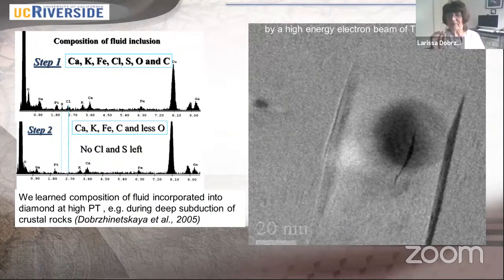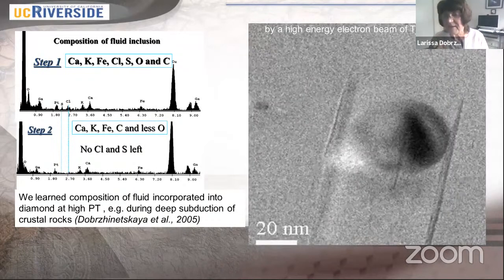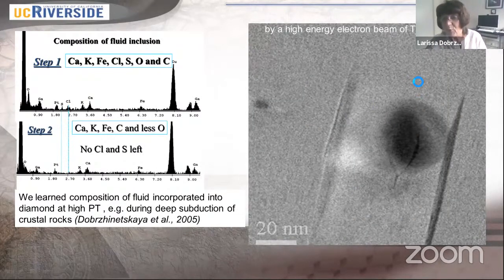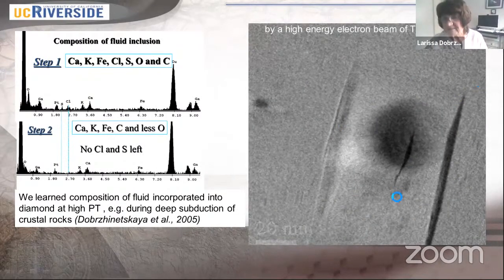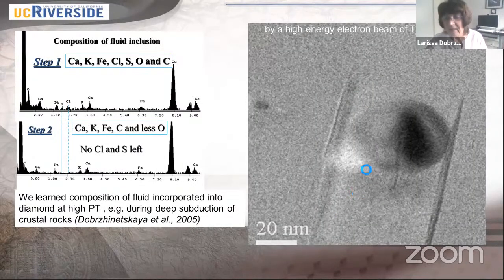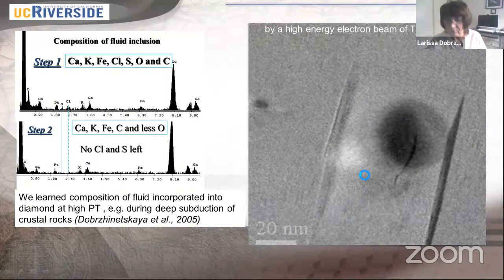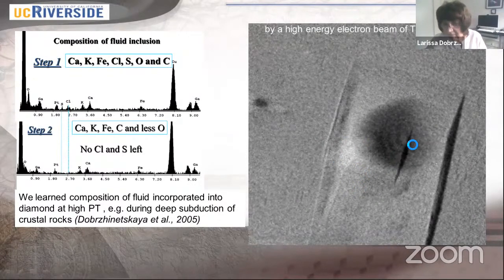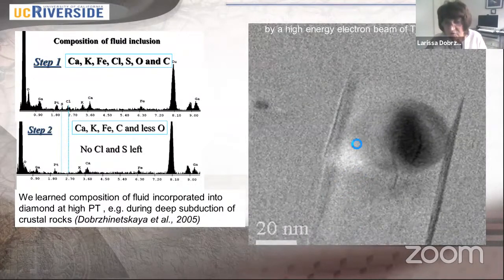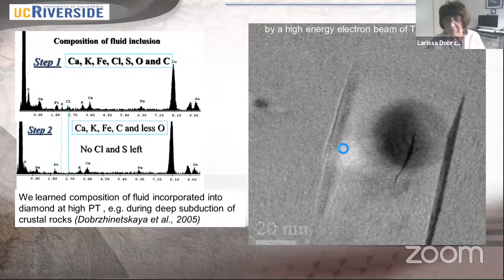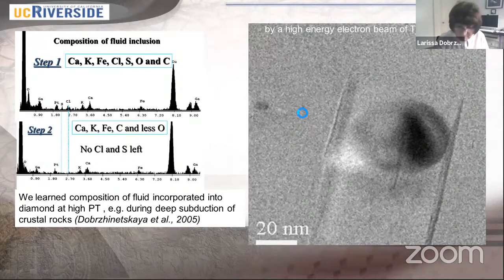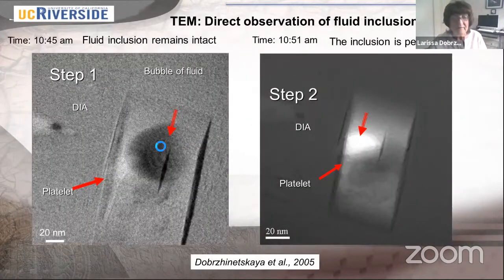Here, you have to start to think very fast. What does it mean? Because you see, it's probably a bubble of gas or fluid, okay? And also you see here, during the movement, you see here the crack, and you see here the contrast became very bright, white. What does it mean? It means that this inclusion will be perforated very soon, okay? Because we have a high energy beam, and it will burn this inclusion.